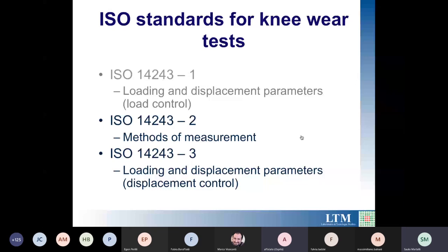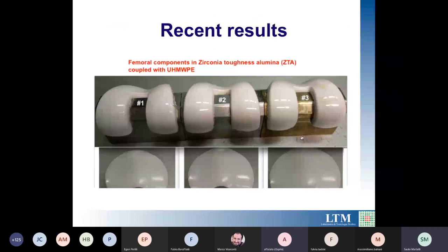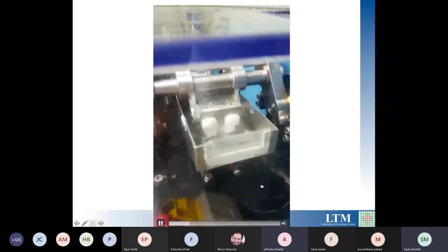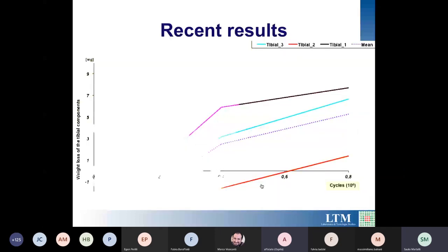I would like to show you some recent results with the use of the knee simulator, in which we tested a new femoral component in zirconia toughened alumina, coupled with the standard polyethylene. This is a view of the simulator in run, with the knee prosthesis against the polyethylene on the knee simulator, and the results are blinded because this test is patented. Anyway, they showed a good comparison with the literature.